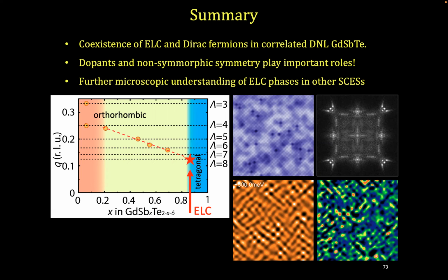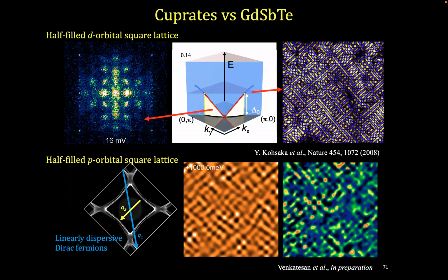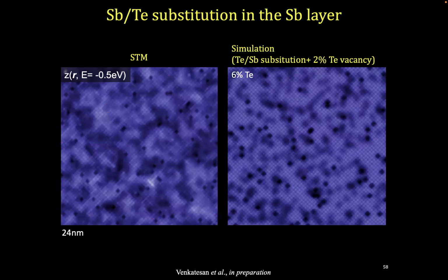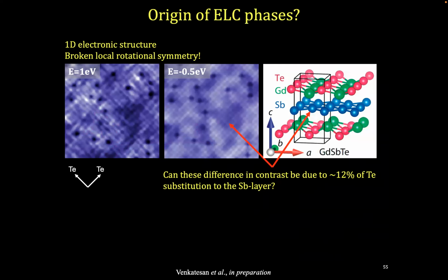Like the doping case, right? So first of all, is this looking at the antimony states or tellurium states? I guess gadolinium tellurium is the surface, and I guess how does the doping work? So the cleave point, the crystal cleave right here. So yeah, it reveals these Te atoms, but the doping actually goes to antimony. So it's electronically the antimony state. Right. It's electron doped. And so the idea is that the tellurium effect, or I guess the absence of tellurium, dopes the system. Right.